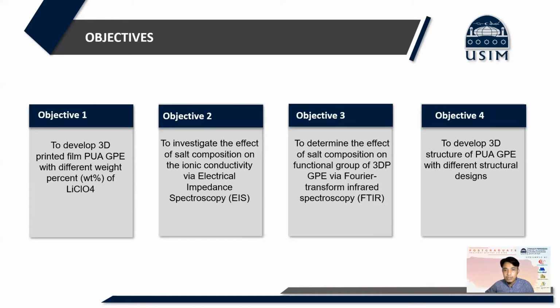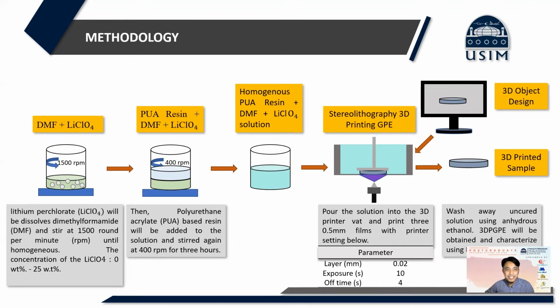And the last one is to develop 3D structure of PUA GPE with different structural designs. This is my methodology. First, lithium perchlorate, LiClO4, will be dissolved in dimethylformamide, DMF, and stirred at 1500 RPM until homogeneous. The concentration of lithium perchlorate will range from 0% to 25%. Then polyurethane acrylate, PUA-based resin will be added to the solution and stirred again at 400 RPM for 3 hours.